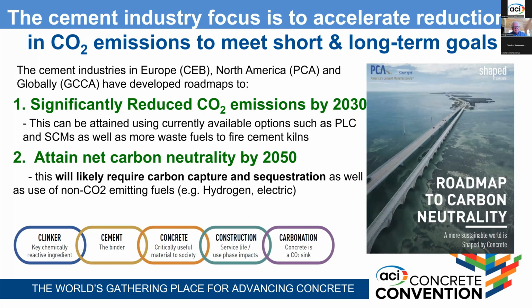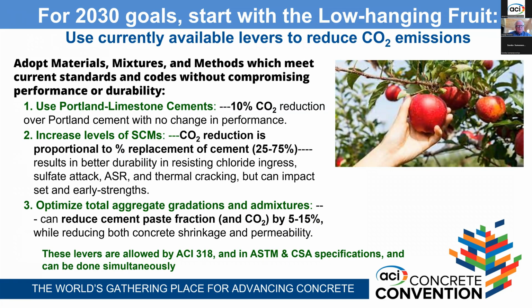And of course, I'm going to go back to that one. There are 5 points on the chain at the bottom. They start with the cement clinker, which is where most of the CO2 is coming from. Then how much clinker goes into the cement that's sold. Then how you minimize the cementitious materials in concrete. And of course, there are things you can do in construction to reduce the amount of concrete that's used, more efficient designs. At the very end of life, or during its life, concrete also carbonates to some extent. So approximately 8% of its initial CO2 is taken up by the concrete in the structures over its service life.